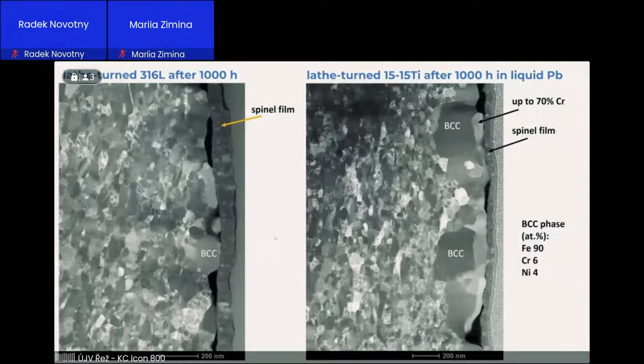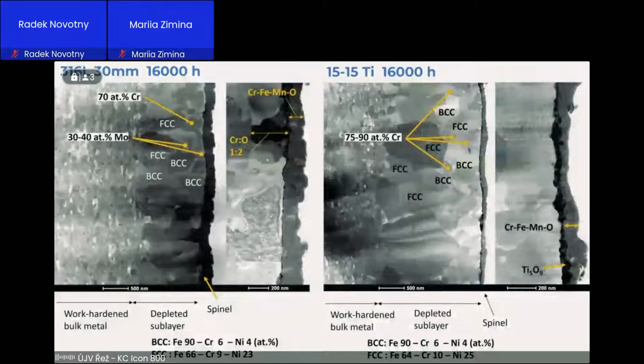A detailed look at this spinel in TEM reveals that there is a growing fine grain layer, which was made by the machining, and new phases are precipitated there with ferritic phase. It's quite interesting. That has this composition, regardless of the material. And after 16,000 hours, this depleted layer became a few micrometers thick, and new phases are precipitated here. The nickel is concentrated in FCC phase, and there is depleted BCC phase accompanied with something that contains a very large amount of chromium. That's similar to spinodal decomposition of delta ferrite in duplex steel, but we have austenitic steel. It's quite an interesting problem.